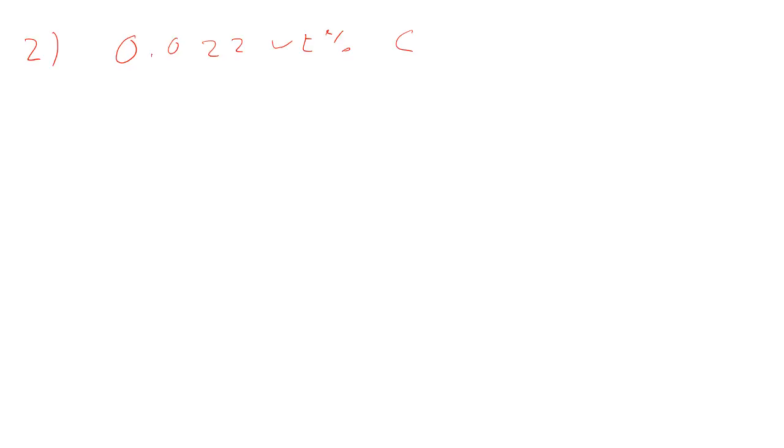Right, so I said the maximum solubility of carbon in ferrite is 0.022 at 727 C. So we assume that we can retain it all in solid solution during a quench to room temperature, and then it becomes precipitated as Fe3C. So not really a physical process, but an idealized kind of process.